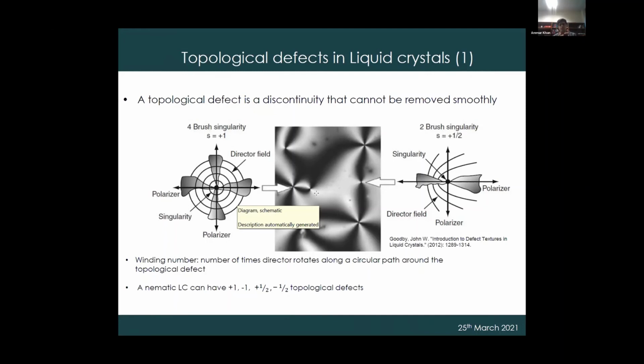For example, if you have a donut, and you have a path that encloses that hole, then essentially you have a topological defect there, right? Similarly, in nematic liquid crystals and in ordered matter, you have these topological defects. Over here, we have a typical nematic liquid crystal viewed under cross polarizers. This is called the Schlieren texture, and what you typically see is that you get these brushes.